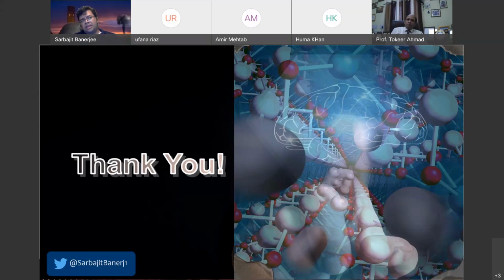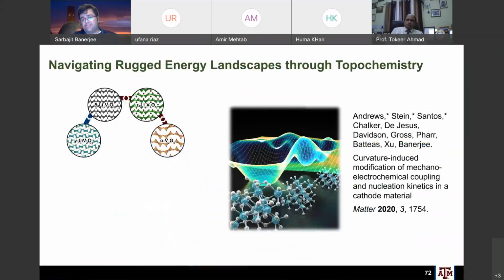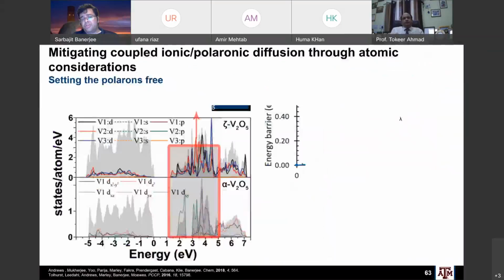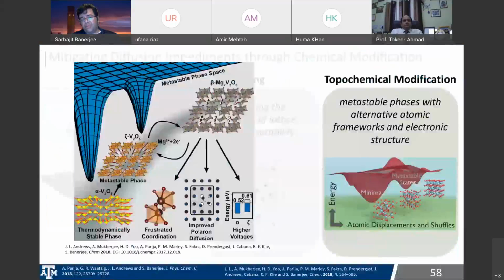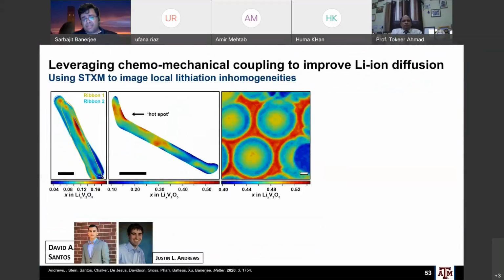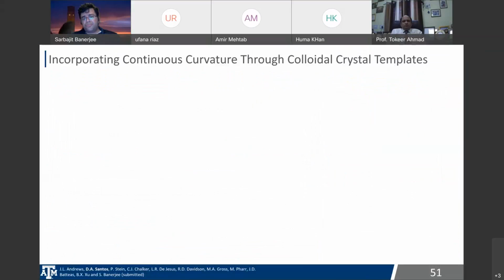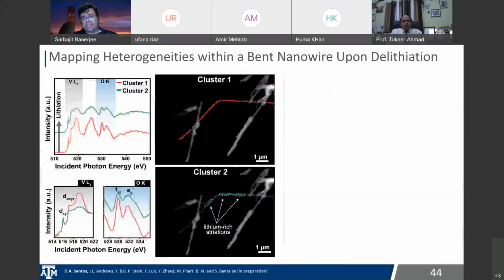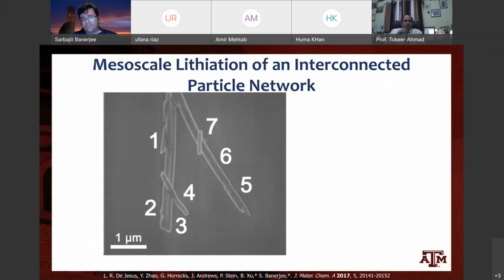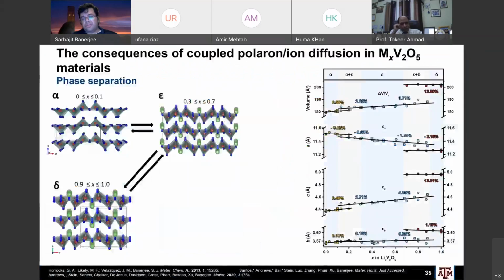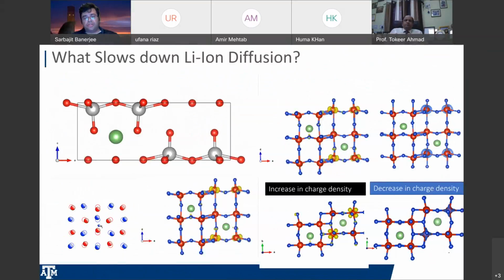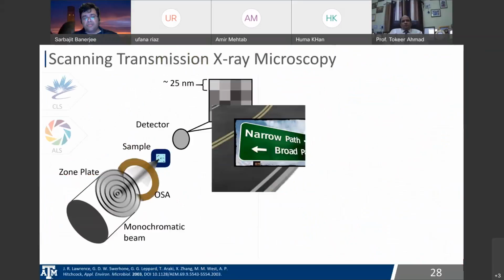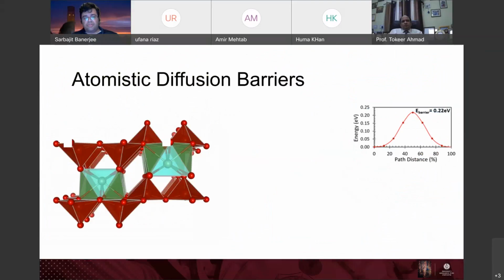So the polaron that I talked about is a direct consequence of the electronic structure, and the polaron is something that is stabilized because of the peculiar electronic structure of this V2O5 phase. And this is something that I think was not fully appreciated before we looked at it. And then once we looked at it and identified the problem, we could think about solving it by moving to alternate structures. And maybe now I'll be able to play the video that didn't play the first time around.